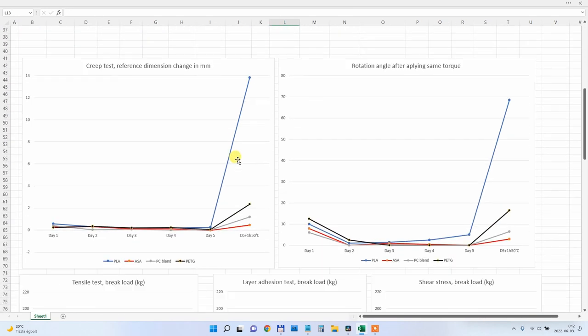Let's analyze the graphs better. So these are those two creep tests with the C-test specimen and with the screw. And I got very similar data. Basically after the second day all three filaments stopped with the creeping except the PLA. So the PLA continuously creeps in this test, and after 50 degrees Celsius in the oven it had a significant amount of creeping on the screw test, and of course in the oven it already failed.